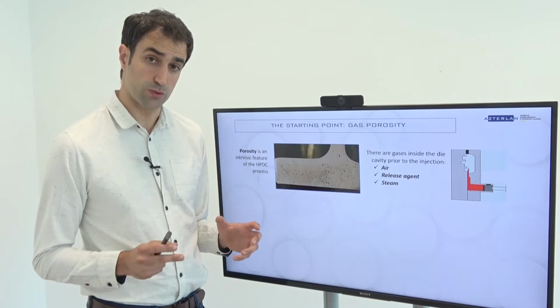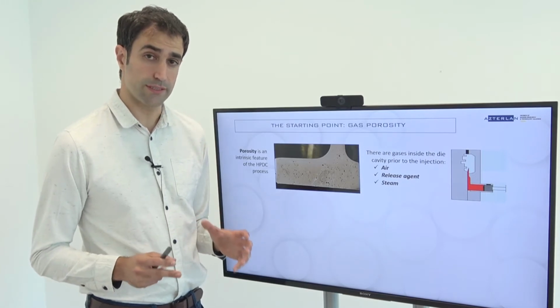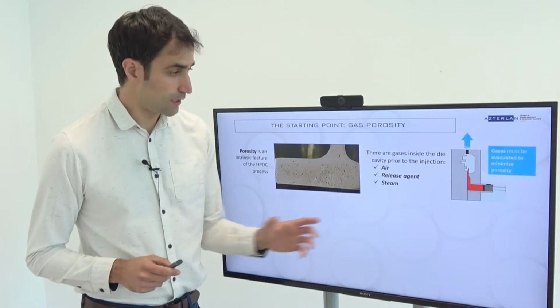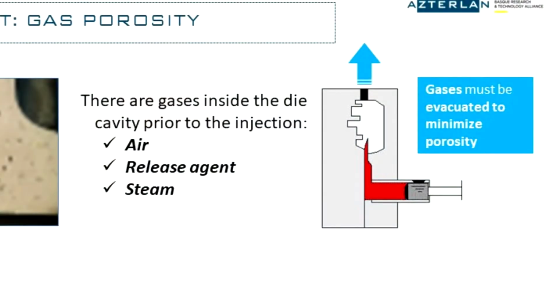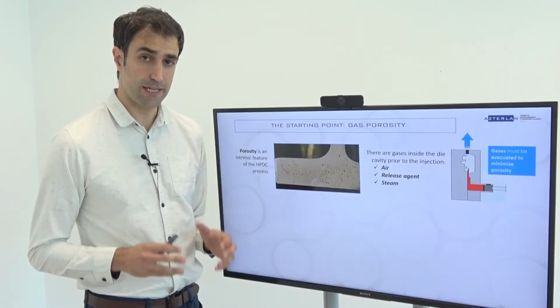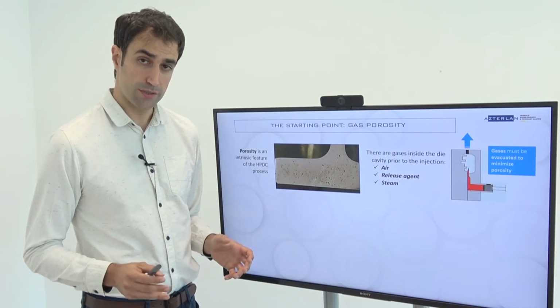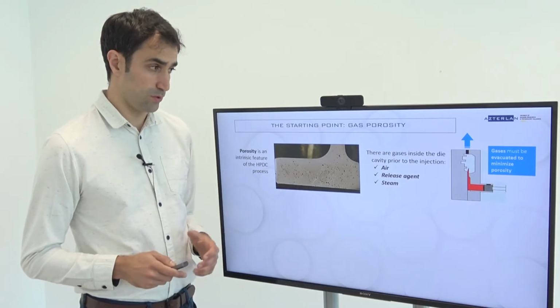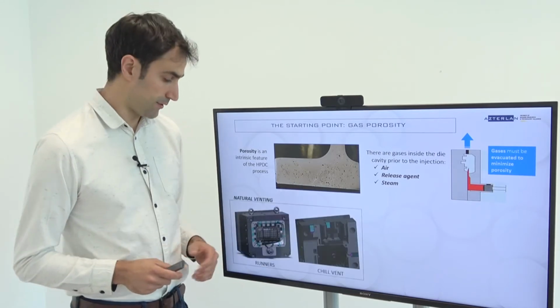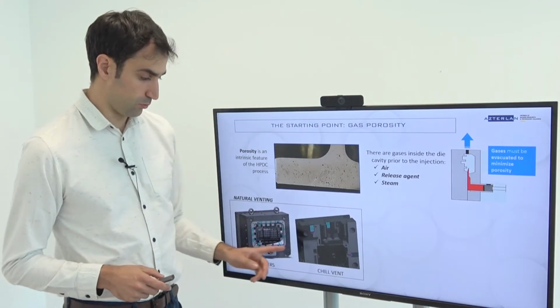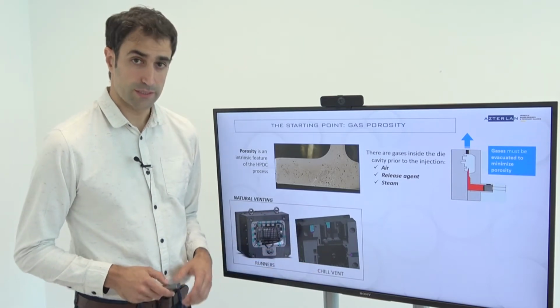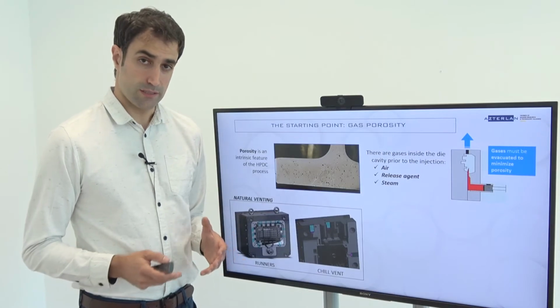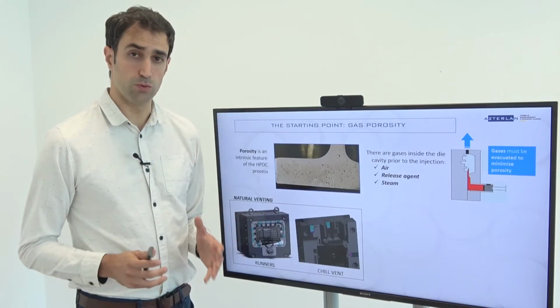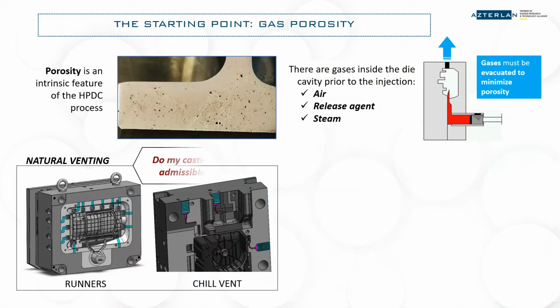So, in order to produce a casting with no porosity, the flow must push the air out of the mold and replace it with molten metal. The problem is that in high-pressure die casting, the aluminum is injected at a high speed, so there is no time to let the air escape from the mold through the natural venting, either with the basic runners or with the more efficient chill vents. The conclusion is clear. Natural venting is insufficient if we want a gas-free component.